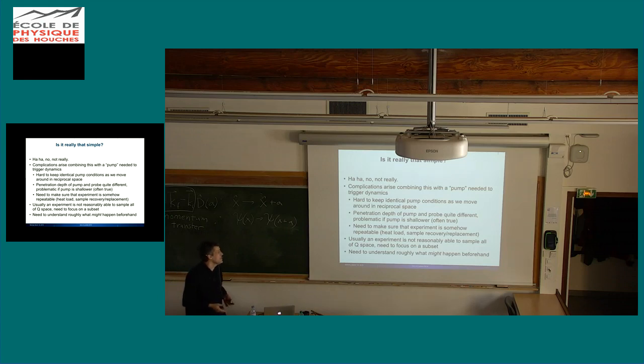The problem is that you need to combine this with a pump to do a time-resolved experiment to trigger the dynamics. Because remember, if you want to look at a coherent phonon, you have to define an ensemble that has an unambiguous time 0. And so you should have a pump if you want to do these kinds of measurements, or you need some kind of reference in order to look at the coherence. It's very difficult to keep identical pump conditions when you're moving around in reciprocal space, because typically that involves rotating your crystal around, so that's difficult.